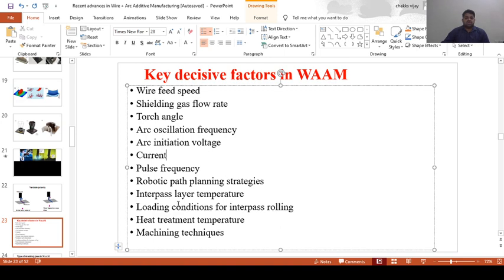Then the next one, the most important one, is the interpass layer temperature. Most lectures never address the importance of this interpass layer temperature. It means, I deposit the first layer, and how much dwell time I take to deposit the second layer. After depositing the second layer, how much dwell time I take for depositing the third layer. That dwell time is otherwise known as the interpass layer temperature. So how much time I am allowing my material to solidify. Initially my metal will be in red hot condition, and if I deposit my material as it is, it would end up with a lot of geometrical irregularities. So to avoid that, we have to maintain the interpass layer temperature.